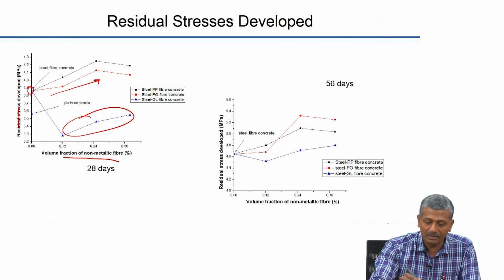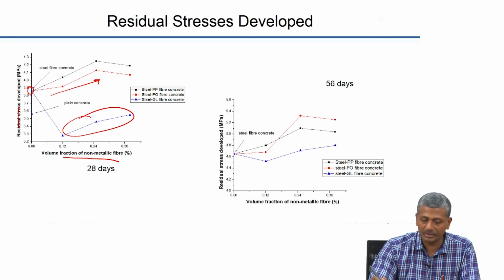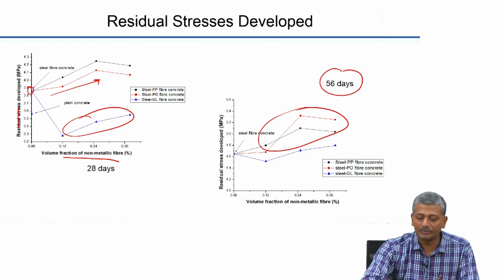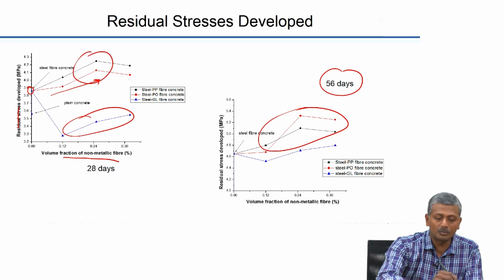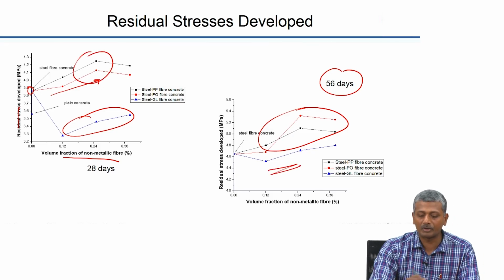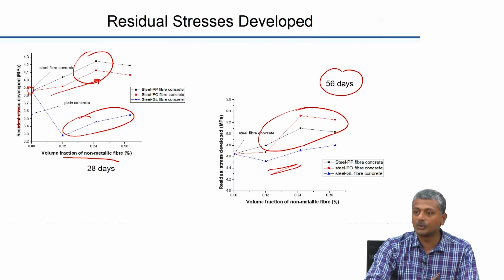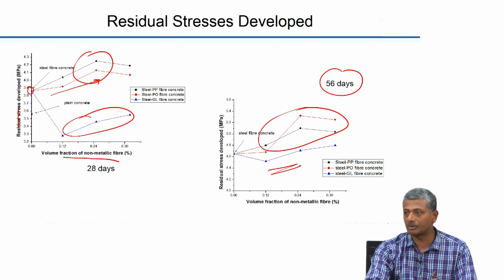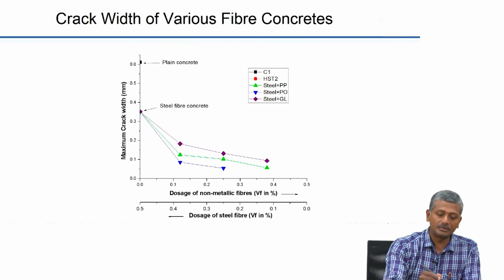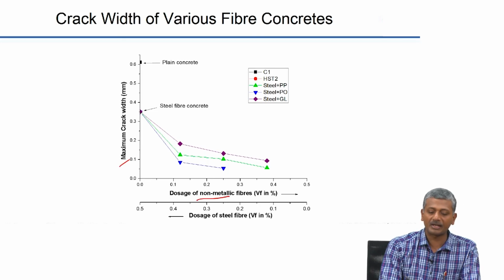On the other hand, if you look at residual stress in terms of 56 days, you see a performance which is similar to what you have at 28 days for the polyester and polypropylene concretes. For the glass fiber concrete, you still have a system that is showing a lower residual stress than the steel fiber concrete. Again, this is showing the maximum crack width versus dosage of non-metallic fiber.